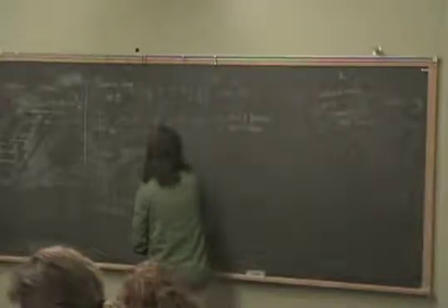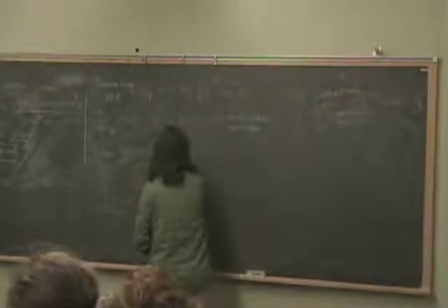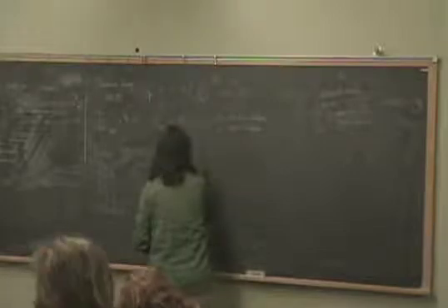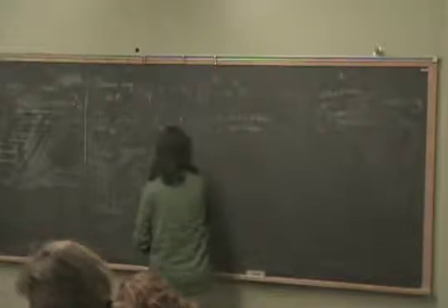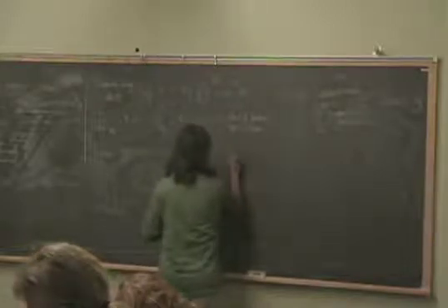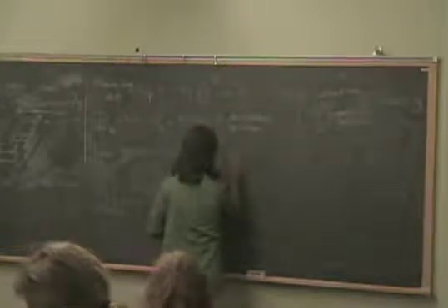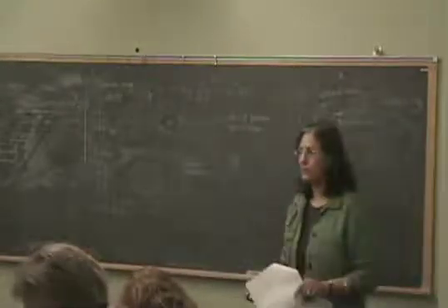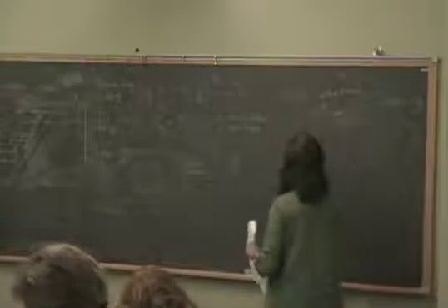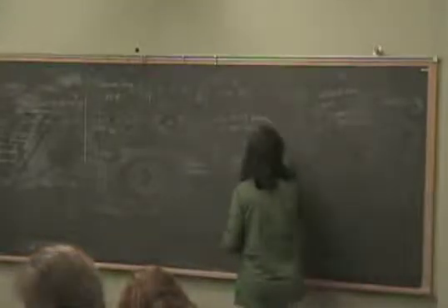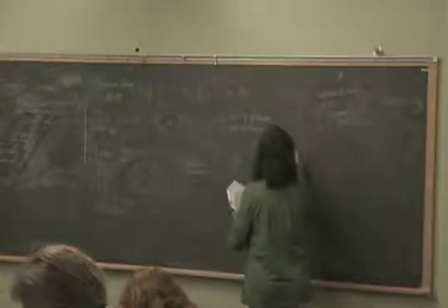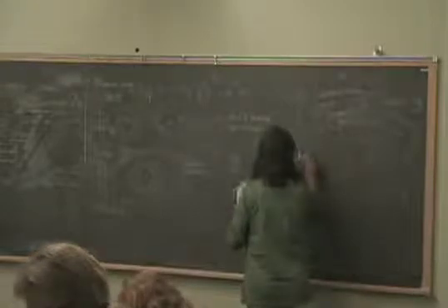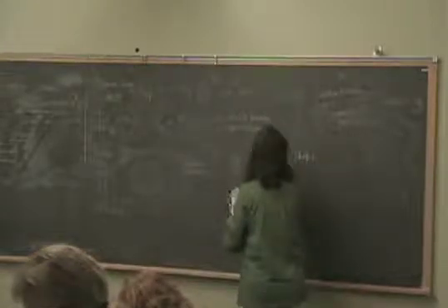Omega surface, it's called a surface plasmon. And for a sphere, this comes out to be omega p over square root of 3. I'm not doing the derivation, it's just doing E&M with a different boundary condition. It is a problem in Ashcroft and Mermin, chapter 1, problem 5.